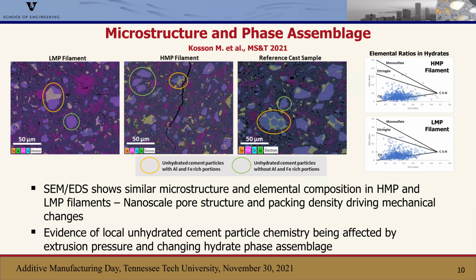As far as the effect of this on the microstructure, what we found is that there aren't big visible changes in the microstructure between these low mechanical property filaments and the high mechanical property filaments. And that suggests that most of the changes are more at the nanoscale, in the pore structure and the packing density of the individual chemical hydration products, as opposed to changes within those hydration reactions themselves. We do see, however, that there is some evidence of changes in the dissolution depending on the chemistry of the unhydrated particles. So I'm not going to get too deep into that for this talk.